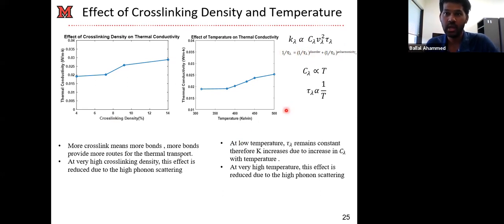So at low temperature, this tau remains constant. Therefore, the K increases because at low temperature we know that the C lambda increases with the temperature. So tau is unaffected at low temperature, it doesn't change that much, or has just less influence. So the thermal conductivity increases mainly due to the increase in the C lambda.